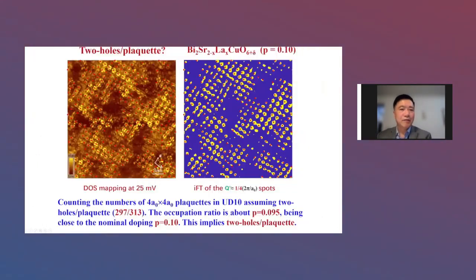To count the hole number, suppose that we have 2 holes on 1 plaquette, then for this 10% doping, we expect about 313 plaquettes, okay? This kind of nematic 4a by 4a plaquette. And we did the analysis, and we found that the total number is about 297, which is 9.5% doping, which is close to the nominal doping.